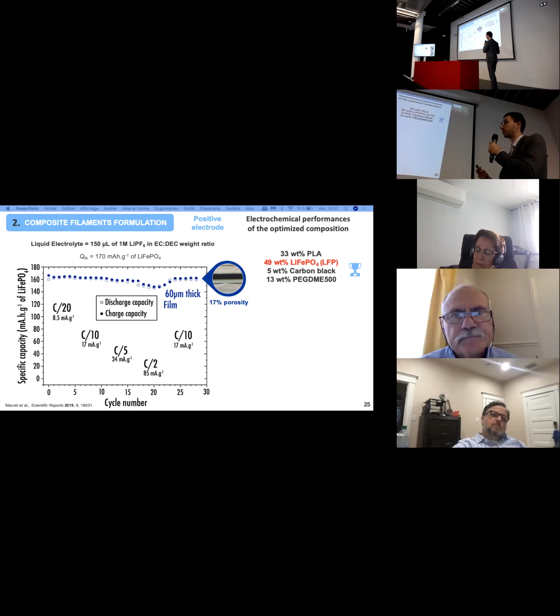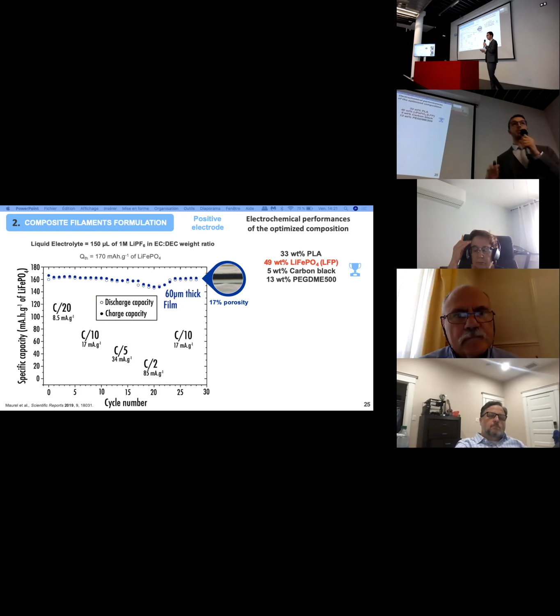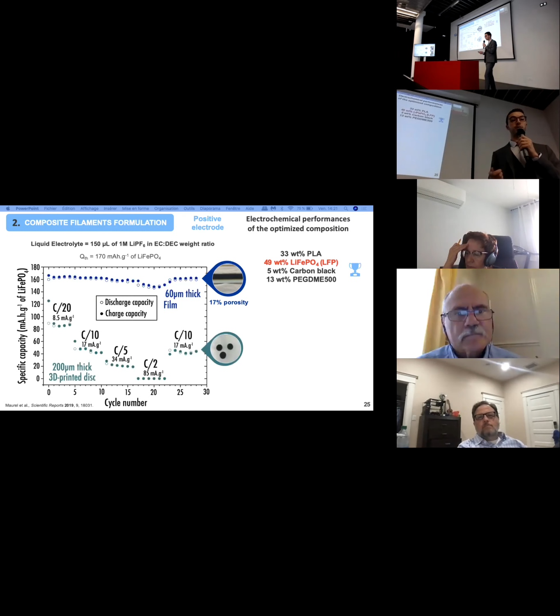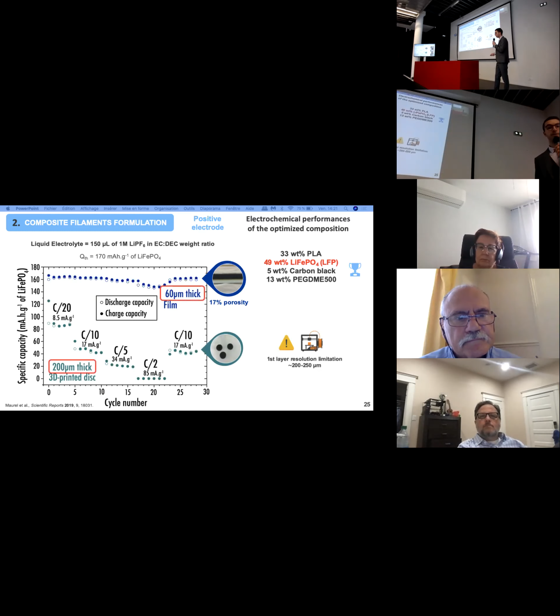And so we decided with this composition to produce classical 1.75 mm filaments and to print some 3D discs. For these 3D printed discs, you can see again that you have a huge gap between the films and the values that you obtain for the 3D printed discs. And here again, this is due to the first layer resolution limitation.